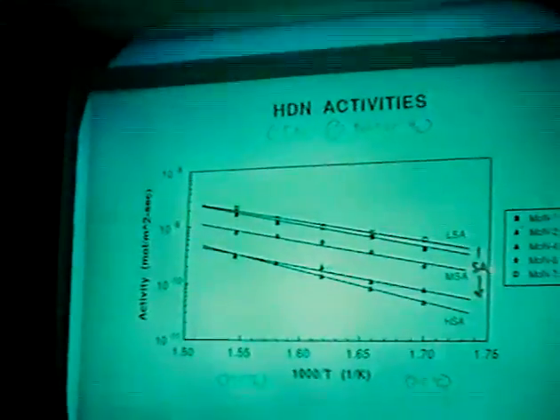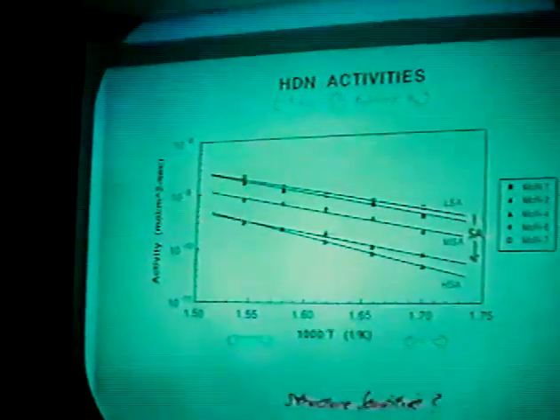You'll notice that apparently things that go through this dioxide produce either medium or low surface area materials, while pathways that go through this bronze produce higher surface area materials. And we believe that that's one of the keys, that and the structural character of the reactions that take place dictates whether we can create high surface area materials or not. For those of you who are familiar with the concept of topotacticity, apparently topotacticity combined with pseudomorphic reactions are what gives rise to these high surface area materials.